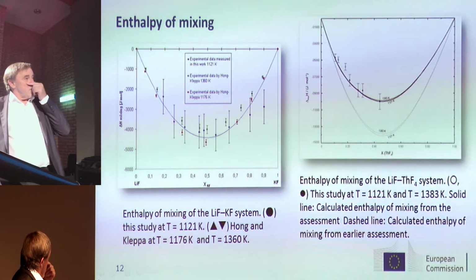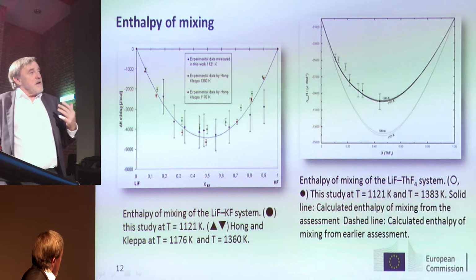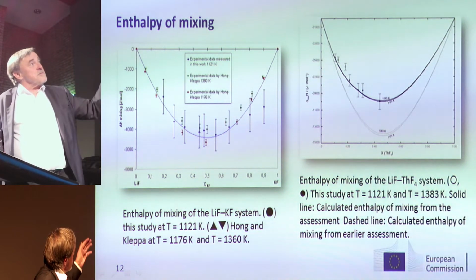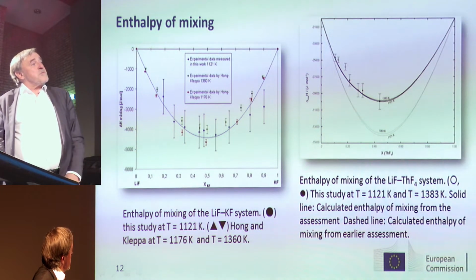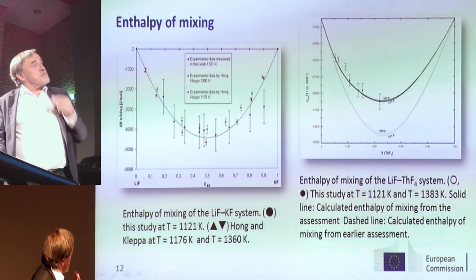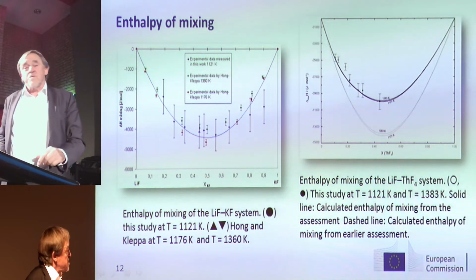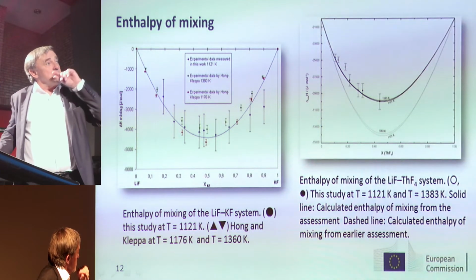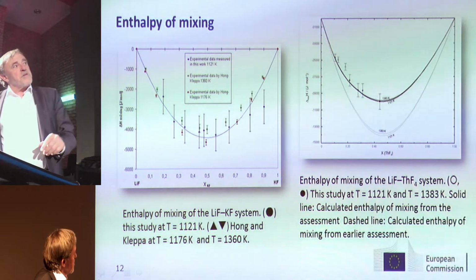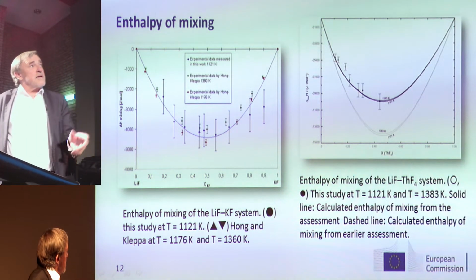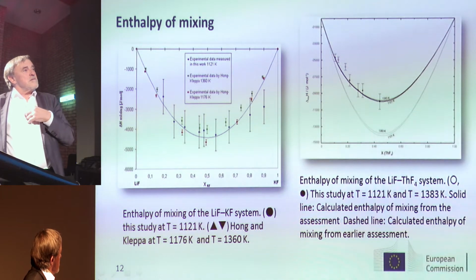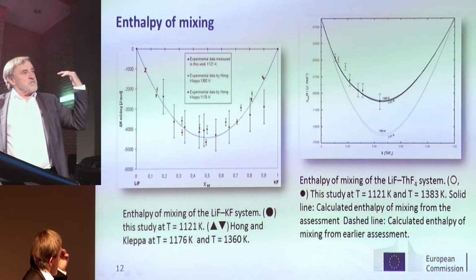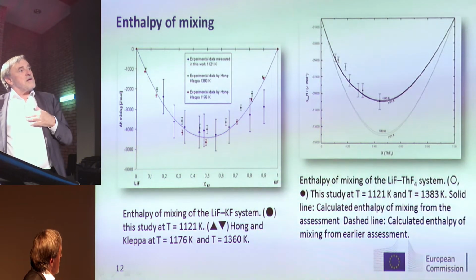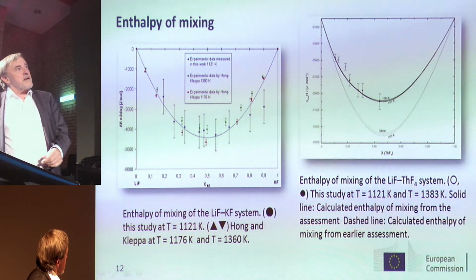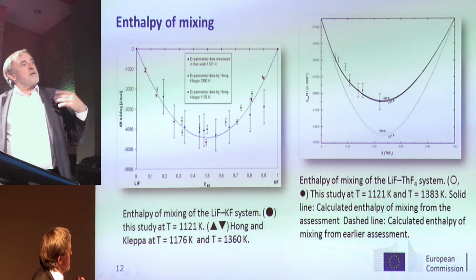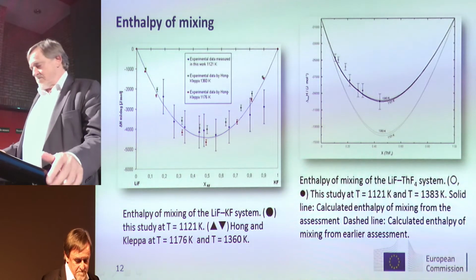This study was done at 1121 Kelvin, and compared to two data sets which were found in the literature, and you see that there's a good agreement between the data in the literature and our data, which we have measured recently, and also very well confirmed with the calculation by FactSage. And on the right-hand side, we have then the enthalpy of mixing of the lithium fluoride and thorium fluoride system. Again, two different temperatures in this case, the solid line, which is the calculated enthalpy, again fits very well for the two temperatures, which are very close, with the experimental data which were measured. They are quite away from an earlier measurement which has been done on a similar system.